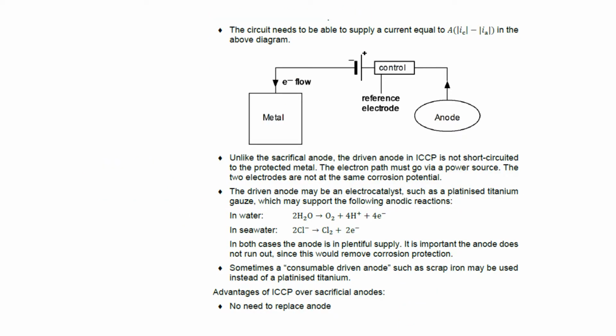Now, we also want to know, what does the schematic of the electronics for an ICCP system look like? And we have this quick sketch here. This shows that you have your metal being protected, a power source, and strapped to the power source, importantly, we have a driven anode. This is important because what I said so far is we're supplying an electron flow to the metal to be protected. That's to supply the net cathode process that takes place on the metal because of the accelerated, unbalanced hydrogen evolution reaction. That net cathode on the protected metal needs to be balanced by a driven anode somewhere else.